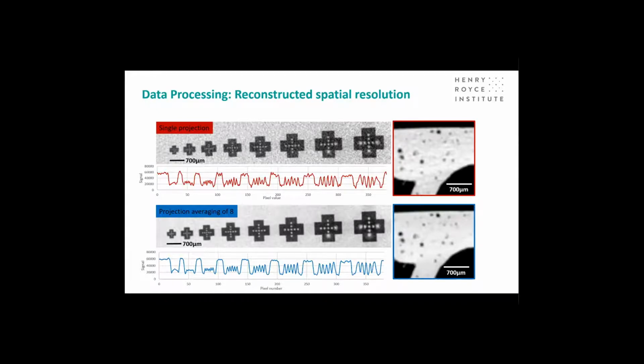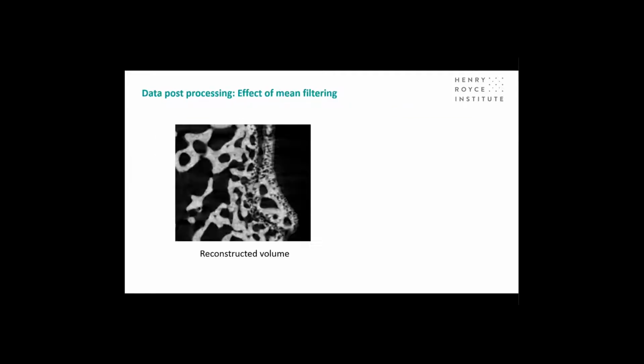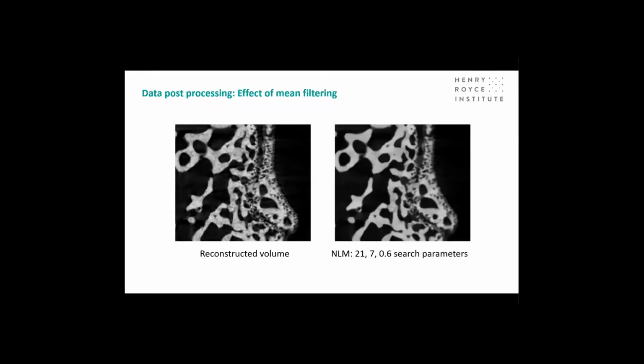And again, you can identify the conditions that you need to be sure that the defect sizes in the part are smaller than the critical defects that you would need to get a particular lifetime. It's also important to remember that when you process the data, you can often affect the results.